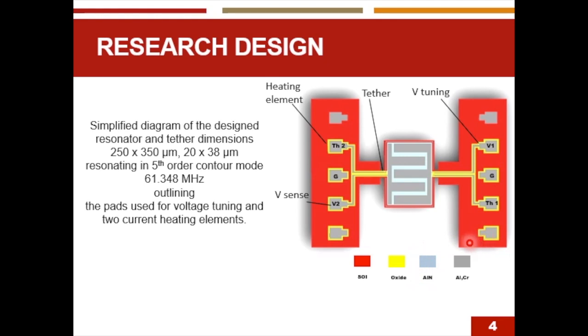This design resonator was designed and fabricated using the PiezoMUMPS process. So we can see the layer SOI oxide and aluminum nitride and the metal layer aluminum and chrome mainly. This resonator resonates in the fifth order contour mode with the frequency 61.348 megahertz.